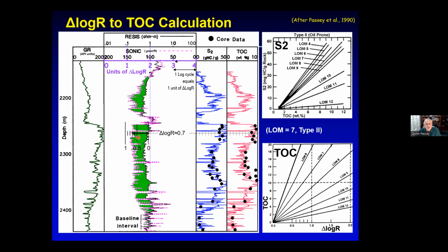And in this case, we can go through and do the overlay baseline here, and we can measure the separation at every point. Maximum separation is somewhere around 0.7. We can then bring it across to our calibration chart. We have the calibration wells, all the data shown in our 1990 paper, but then we can go in. We know the maturity of this is just entering the oil window, and then we can come off and calculate what's the log predicted TOC and S2 in this case because it's in the oil window.